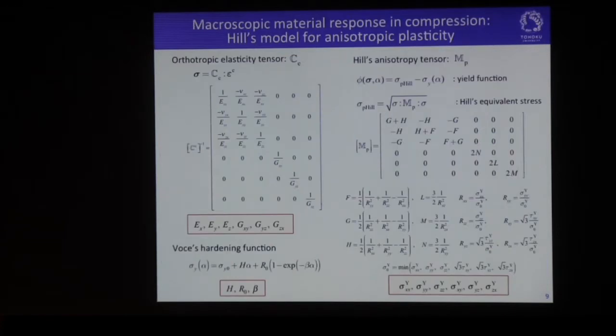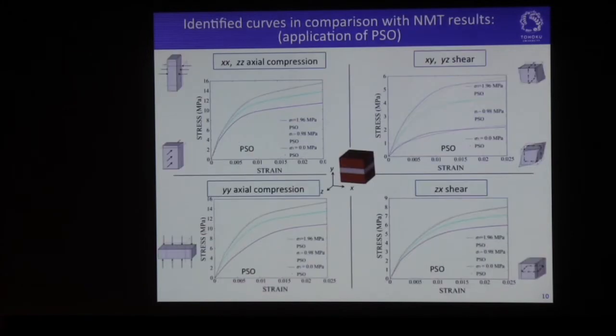Okay. So in order to represent such kind of anisotropic response, we employ the Hill's model for anisotropic plasticity as well. And this is the standard orthotropic elastic tensor for the generalized Hooke's law. And this is the standard expression for the yield function by using Hill's equivalent stress. So we don't need to explain the detail, but here we have the material parameters to be identified. So again, we apply the particle swarm optimization to identify the material parameters. Here are the identified curves in comparison with the numerical material test result. The two curves are almost identical, so you can see the identification was quite successful, as you can see.